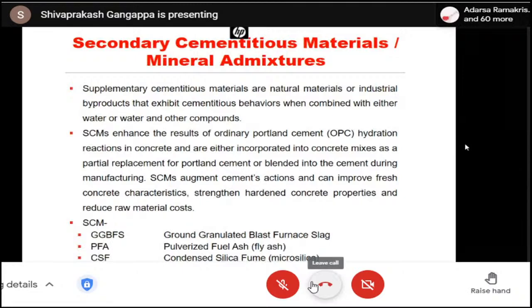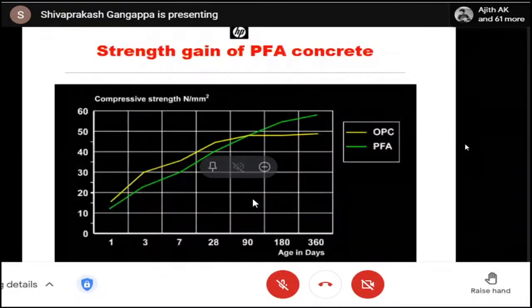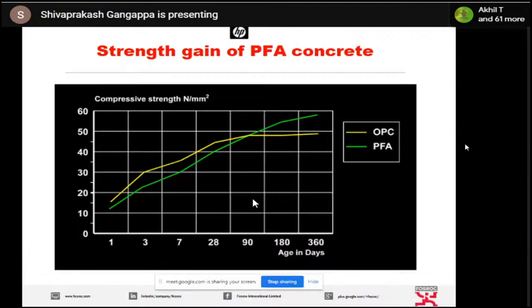In order to incorporate this secondary cementitious material, first of all, we should know its behavior. What is the behavior of this? If we take fly ash, you could see two graphs here. One graph with a yellow line, the other graph with a green line. Same mix, no change. We have used about 400 kg of OPC cement. Sorry, the yellow line is the OPC cement, and the green line is 300 kg OPC and 100 kg fly ash. That means I've replaced about 23 or 24% of cement. In the initial days, what happened? Your OPC concrete, which is the yellow color, will give you a higher strength. But the concrete with fly ash will give you lower strength. But as the age goes, at 90 days, what happens?